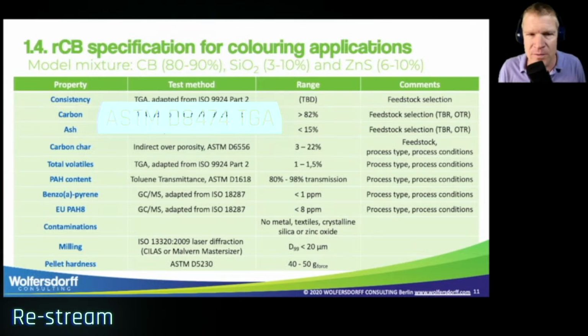TGA is a thermogravimetric analysis, and it analyzes how much volatiles you have, how much carbon and how much ash in the recovered carbon black. We can adapt the method ISO 9924 Part 2 for the TGA, measuring the consistency. If we don't have a consistent TGA result, it's very difficult to have consistent application results.